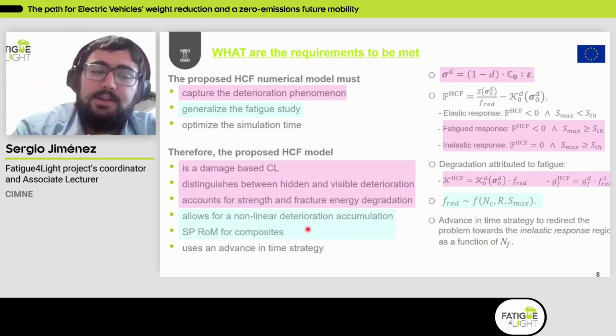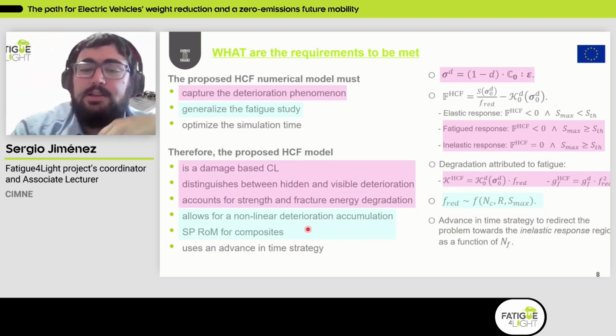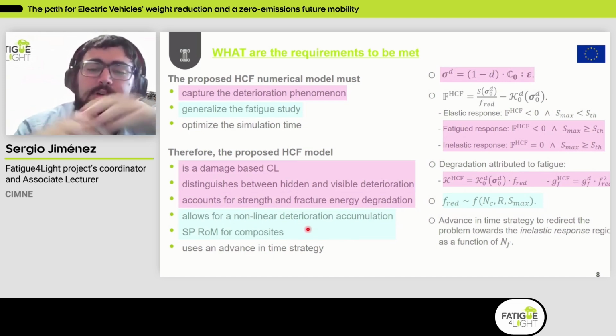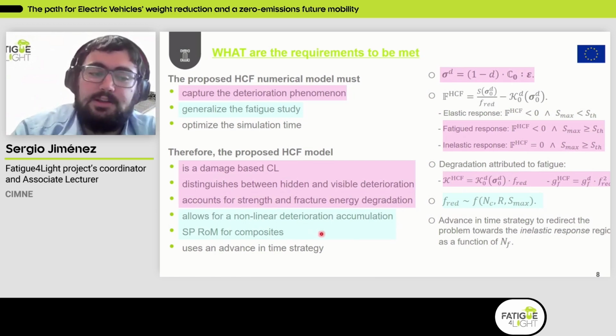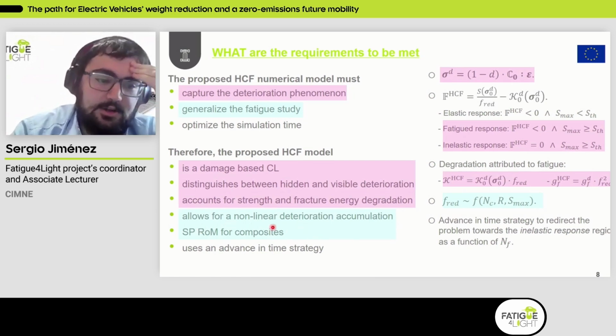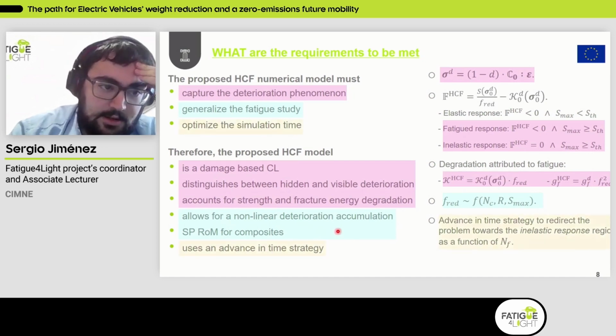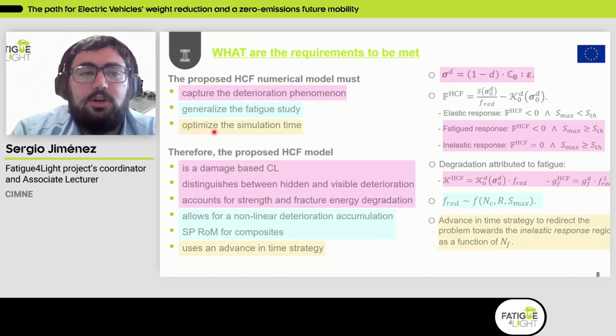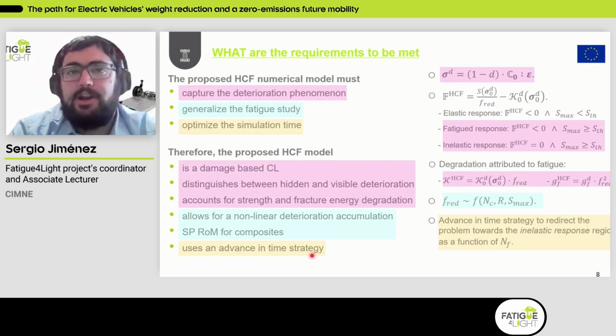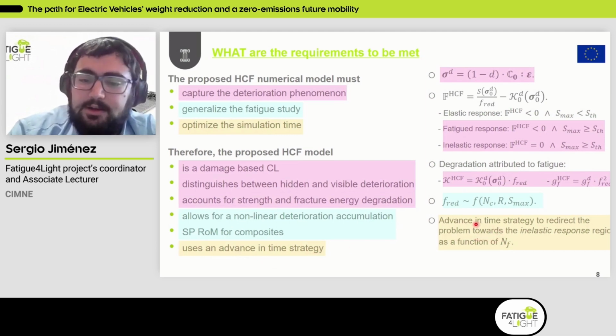So we build up the composite response based on the component, meaning that if we change the component, the volumetric fraction or the stacking, we can automatically apply those changes in the composite response. And then we need to work towards an optimized simulation time from this numerical model. And we are tackling this issue by introducing an advancing time strategy in our numerical model, which basically